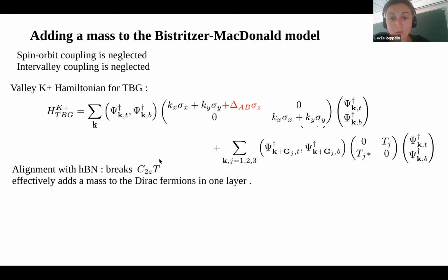I want to focus on that aspect, the fact that you are breaking C2T symmetry. This is just due to the fact that boron nitride has two types of atoms, so it will act differently on A and B sides when it's well aligned. Twisted bilayer graphene, similarly to single layer graphene, has its Dirac cones protected by this C2T symmetry. So by breaking the sublattice symmetry, you break the C2Z symmetry, which in the end breaks this product of symmetries. So effectively, this is like adding this sigma Z term in the Hamiltonian.